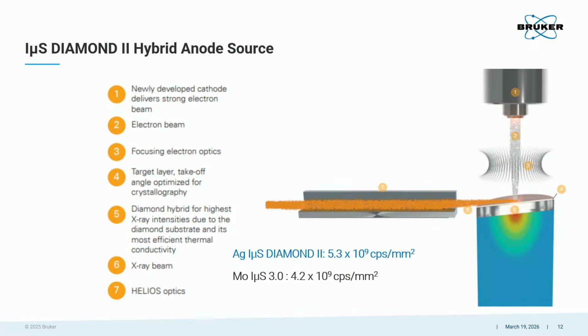We want to have a very small electron beam because this is where heat dissipation works best. If the beam is very small, we're not limited by the diameter, by the circumference of where the heat dissipation works best. It's a two-dimensional problem. And now we have silver deposited on the diamond heat spreader. We get rid of that heat very efficiently.